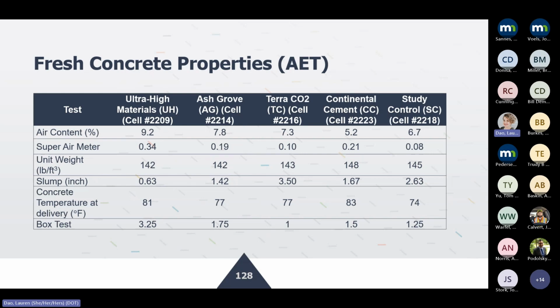And then, as you can see, most of the properties are pretty similar to what you would expect from your conventional paving mixture that is shown on the very right, the study control. And then with ultra high, you see some glaring issues there. The air content is 9.2%. So the issue was, as I will show you in a little bit, initially they did have some problem dialing down the mix.